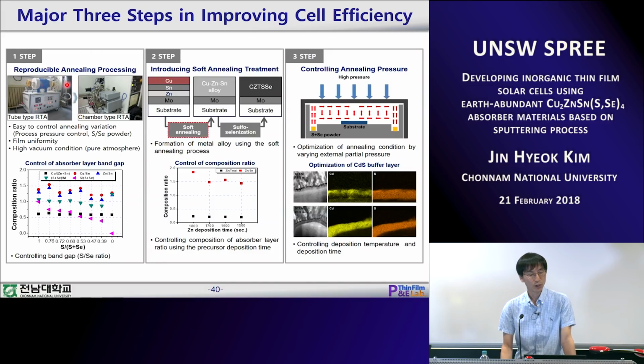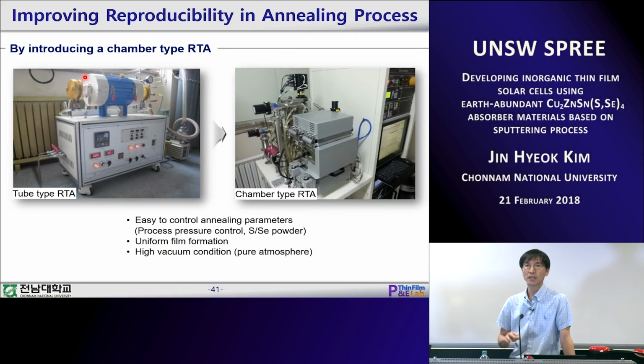To do this annealing process with very good reproducibility, the first thing we did was change the furnace. Initially, we used a tube RTP furnace, this tube type RTA equipment. From this tube type, we changed to a chamber type RTP process. By changing this furnace, we could control the annealing parameters much more easily, and we could make the samples more uniformly. Like we could control the process pressure, the sulfur-selenium powder ratio, and the uniform film morphology. So this is one step that changed our cell efficiency dramatically.